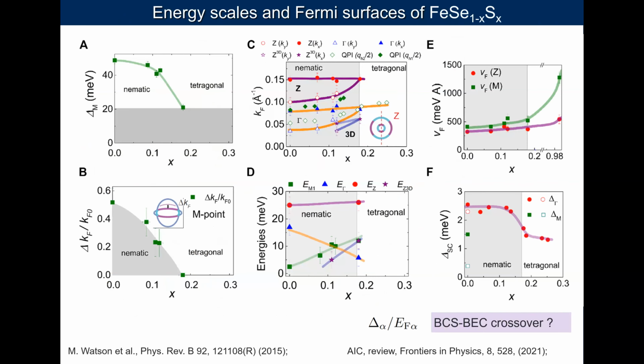Okay, well, this is just a summary of the data we got to characterize these nematic phases. Obviously, the most obvious behavior is that the pockets distort, and we can quantify this degree of distortion. Both these are for the hole pockets, and these are for the electron pockets. The energy scales are quite small, but still up to about 20 milli-electron volts.